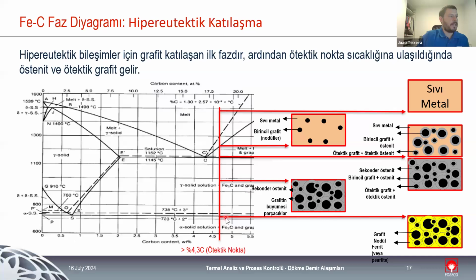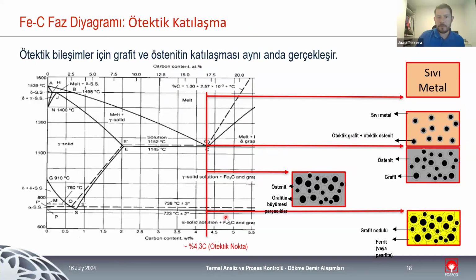And the last stage, that is a mix of hypo and hypereutectic, is when we have what is called eutectic solidification. So when we are really close to the eutectic point, and again, we call it the eutectic point, but it's an area, a small area around the eutectic point, around 4.3%, austenite and graphite grow almost at the same rate. Most of the applications tend to look at this type of solidification because we have the best of both worlds. We have the expansion of graphite and the solidification of austenite happening at the same time. So to counteract some problems like shrinkage and porosity, normally this is the type of solidification that companies try to achieve. It is not easy because it's a smaller area